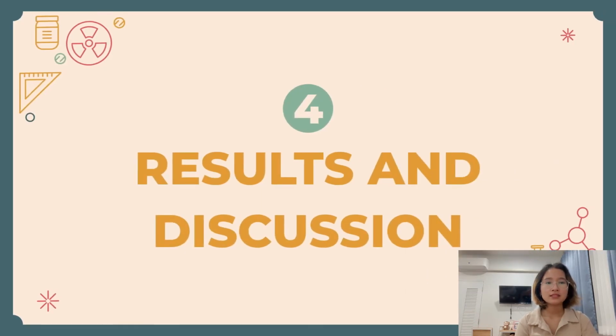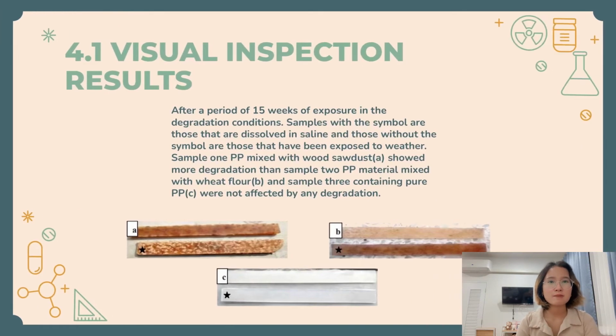The fourth, result and discussion. Visual inspection result. After a period of 15 weeks of exposure in the degradation condition, samples with a symbol are those that were dissolved in saline, and those without the symbol are those that have been exposed to weather. Sample 1, PP mixed with wood sawdust, shows more degradation than sample 2, PP mixed with wheat flour, and sample 3 containing pure PP was not affected by any degradation.